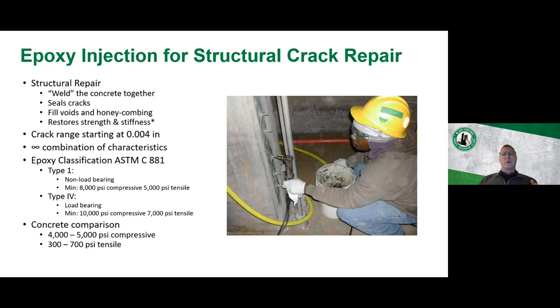Not only is it repairing cracks, but if you're having honeycombs or voids, this is a phenomenal way by which to get the material into the concrete element that you're trying to repair, because it can travel 3, 4, 5 feet through the concrete, even farther, and be able to fill and restore voids.